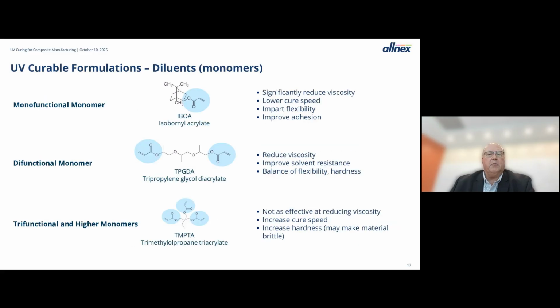So those are the basic oligomers. The diluents were generally characterized by how many different acrylates are on them. So monofunctional monomers, difunctional monomers, tri and higher functional monomers. The lower functionality materials are generally better at reducing viscosity, but are a little bit slower in cure speed. And when I say slower, that's still relative to the other types of UV cure speeds. So everything is going to be very fast. It's just within that very fast realm, the monofunctional materials are slightly slower and the higher functionality materials are slightly faster.